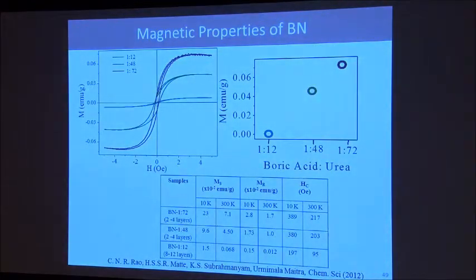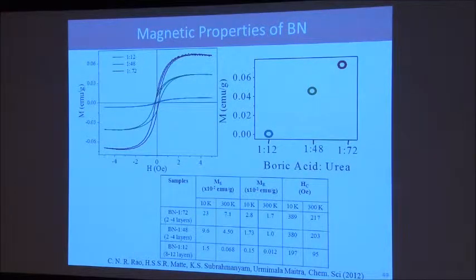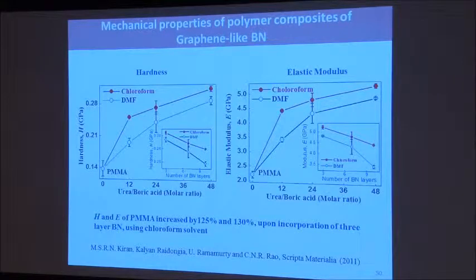And now we have also studied magnetism of these materials and shown they are also magnetic, single layer being most magnetic. Very interesting is many people use boron nitride to strengthen composites, and what we try to show is that if you put a single layer or 2-layer boron nitride, it is a much better material to make composites than ordinary boron nitride.